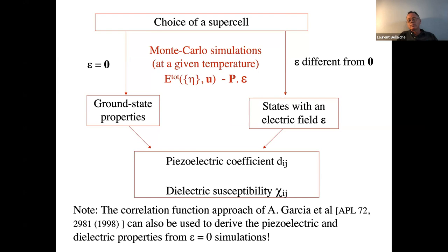In that case, you add a term to the effective Hamiltonian. It's minus P dot E, the product between polarization and electric field. And then you get states that minimize energy that depends on electric field. You compare these two kinds of calculation. You can get the piezoelectric coefficient. You can get the electric susceptibility. In fact, you can be much smarter than that. There's a beauty in statistical mechanics that tells you that even if you do only calculation for which there is no electric field, you can derive piezoelectric and dielectric properties via cumulant approaches. So this is usually what we do. We usually get physical responses by cumulant approaches using no field.